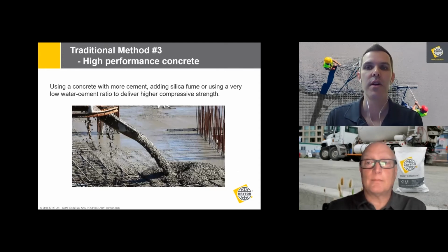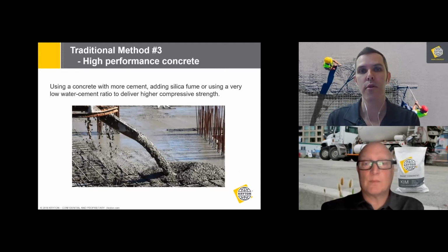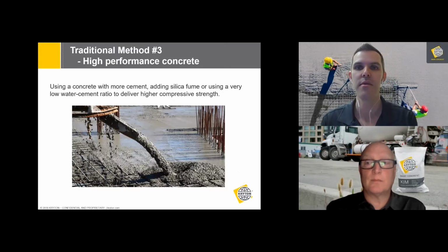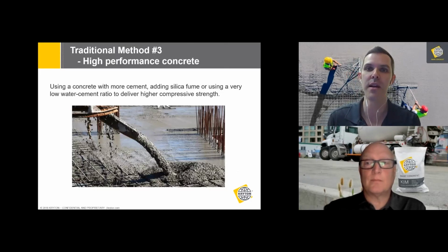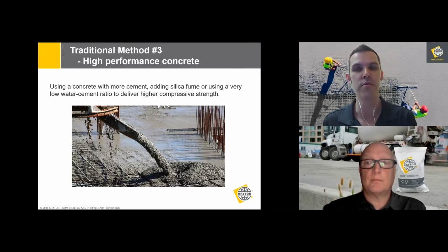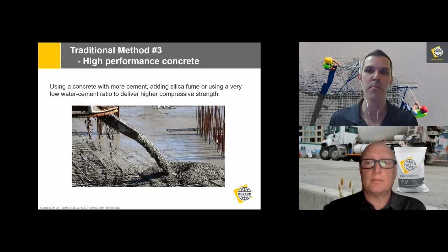Now, if you're not using dry shakes and you're not using a liquid hardener, the third option many people will turn to is, why not just use higher strength concrete? We already touched on it at the beginning. Abrasion resistance broadly correlates with strength. So why not simply use higher strength? You can add more cement powder, you can increase fly ash or slag, you can use silica fume, you can keep the water cement ratio very low. There's lots of options to increase your strength, and you can normally increase your abrasion resistance along with it. So why wouldn't everybody do this?